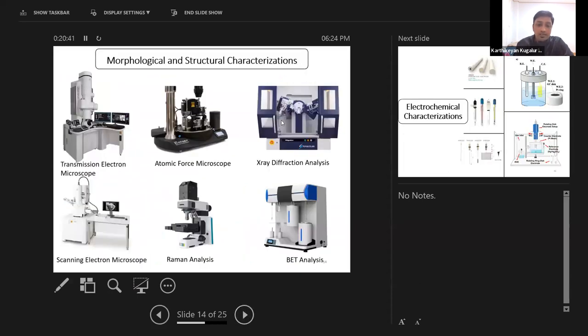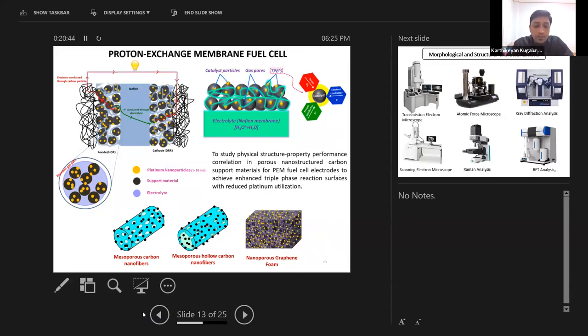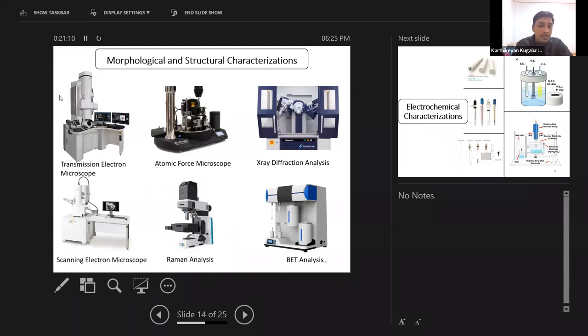So, the morphological and structural characterization. Whatever nanofiber you are producing based on the electrospinning method has to be characterized: the structure has to be characterized, and the morphology has to be characterized, whether it is solid, or whether it has so many beads, or whether it has so many pore structures, and what composition is present in the material. That has to be characterized using various instrumental techniques. Mainly we are using transmission electron microscopy and scanning electron microscopy, and also atomic force microscopy, for analyzing the surface morphology. XRD and Raman analysis will be used for the structural characterizations. And BET analysis will be used for the porosity and surface area characterizations.